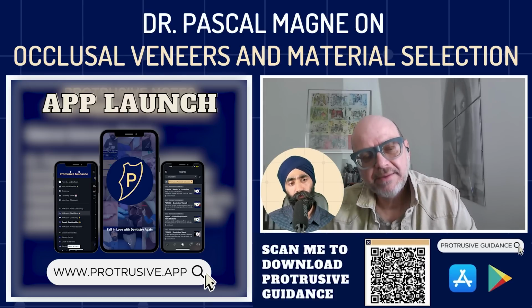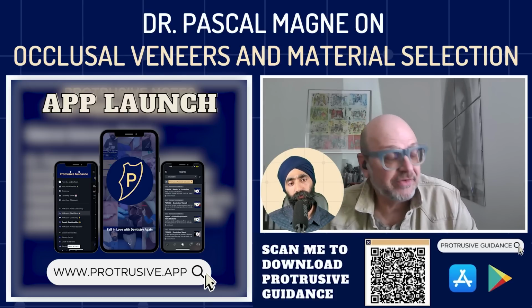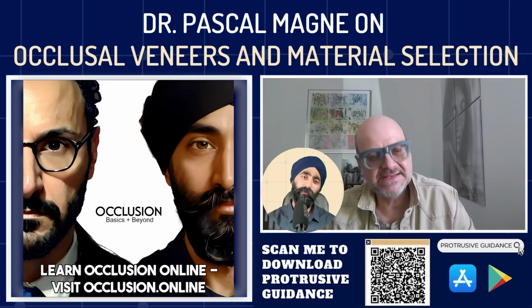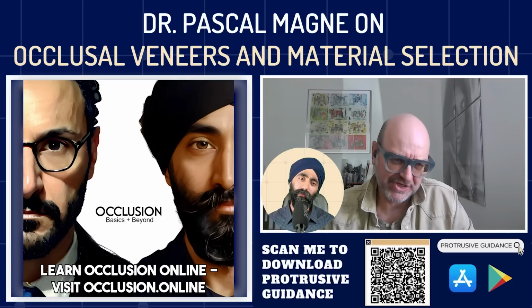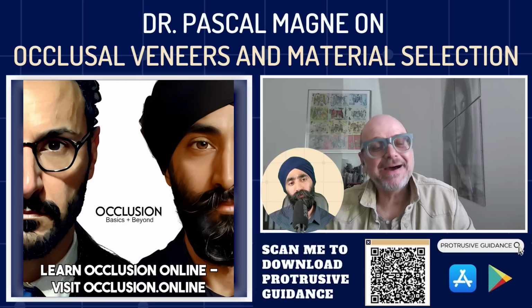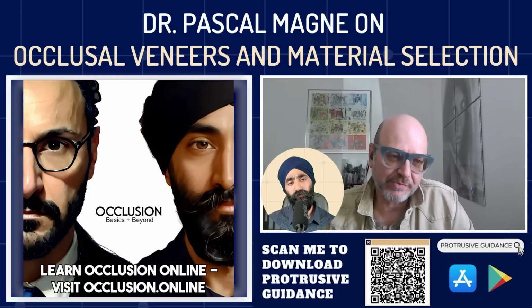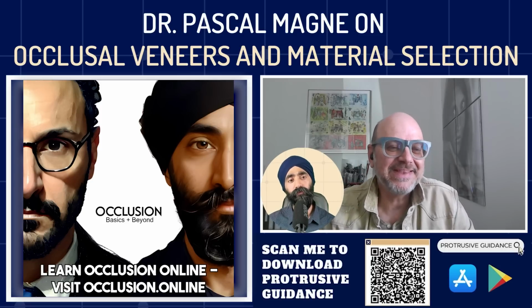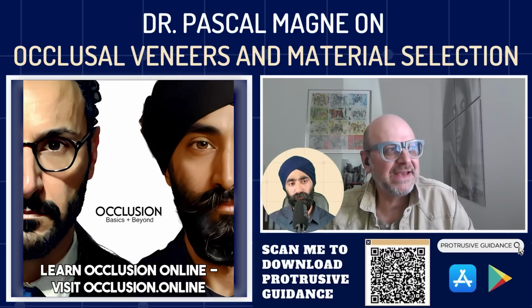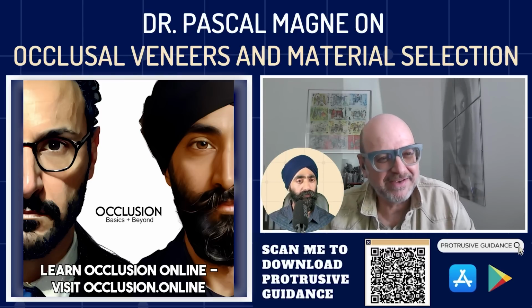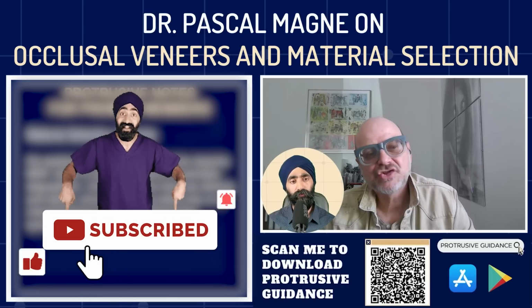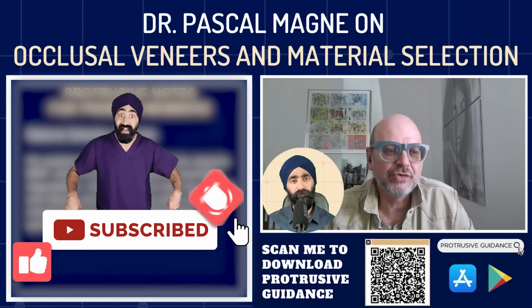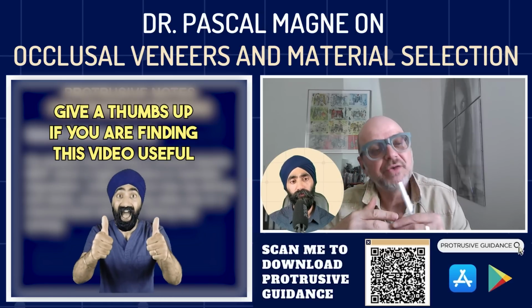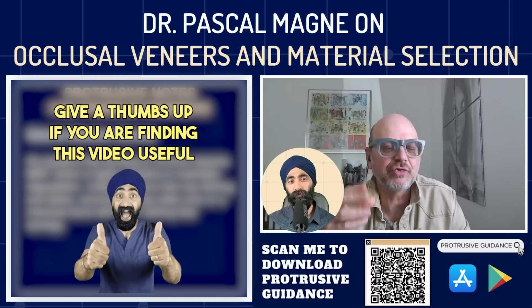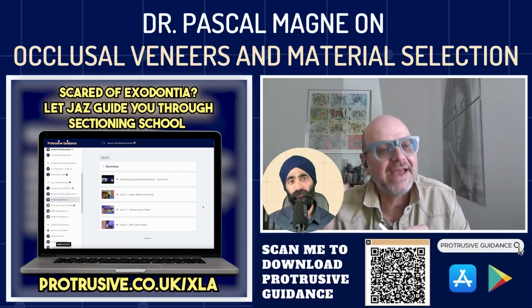Okay. But the problem with zirconia is different. The problem with zirconia is it's extremely difficult to adjust. And I would say it might not be as predictable for bonding. So you need MDP. MDP will be highly sensitive to hydrolytic degradation, the bond. So when you bond ceramics, we do two things. We do etching and silane, and there's synergy in there. With zirconia, you don't have that synergy. It's only a chemical bond with the MDP.